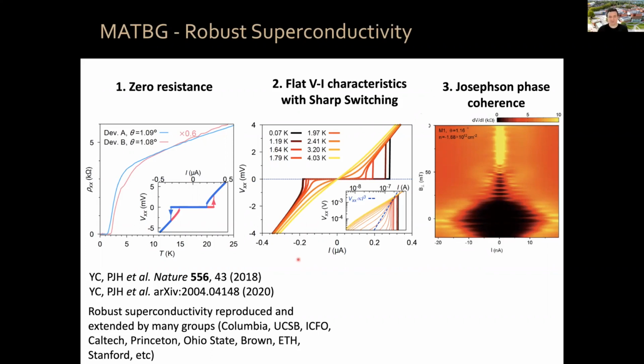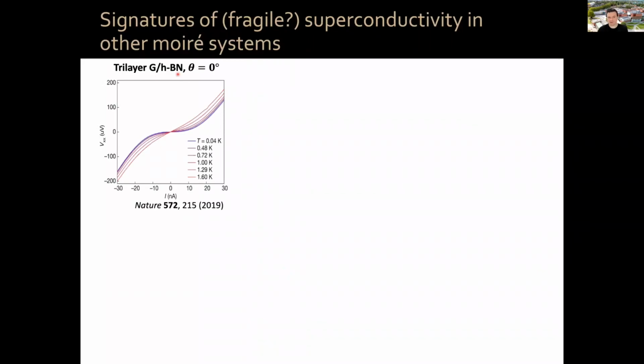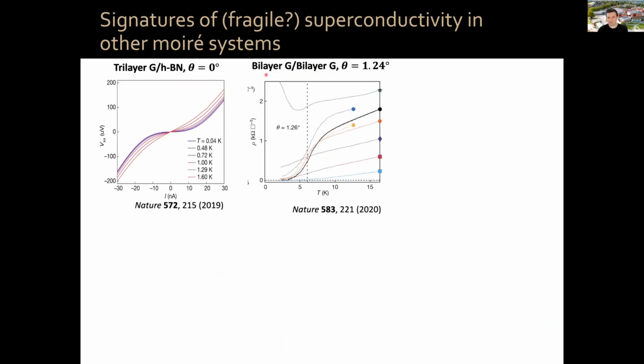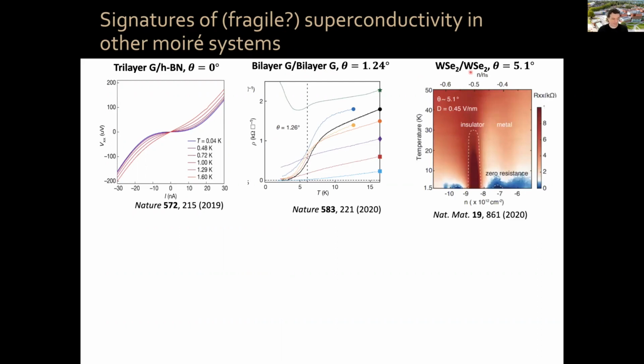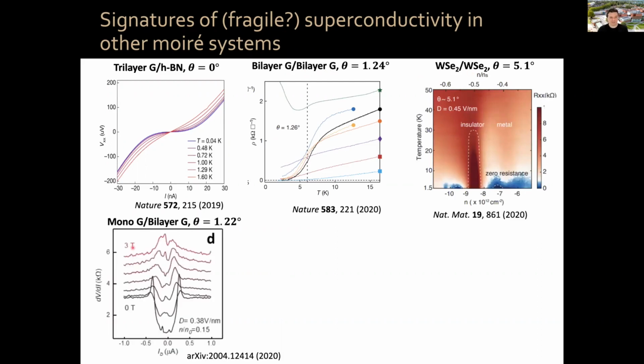Now, this is a little bit in contrast to the more fragile superconductivity in other Moiré systems. For example, trilayer graphene on hexagonal boron nitride, where there is some sign of superconductivity; bilayer graphene on bilayer graphene, so twisted bi-bi; twisted transition metal dichalcogenide heterostructures; and monolayer graphene on bilayer graphene, which is the latest system. In all of these systems, there is typically a key signature, which is a resistance versus temperature curve that transitions to a low, even zero resistance state. Like this data for twisted bi-bi, in some places in the phase diagram you can see that the resistance goes down, actually to zero.